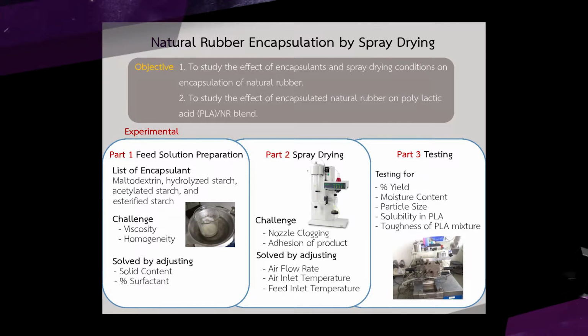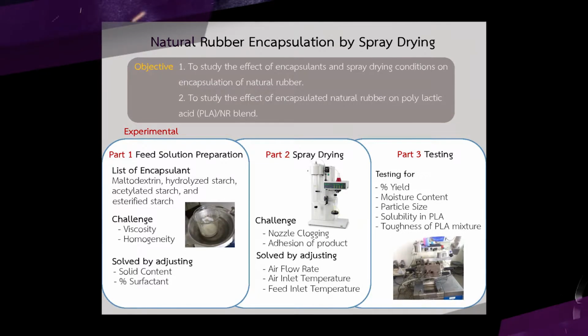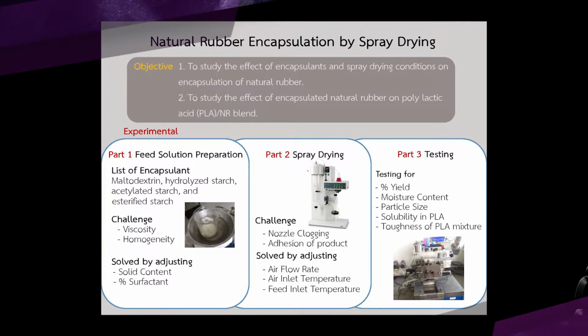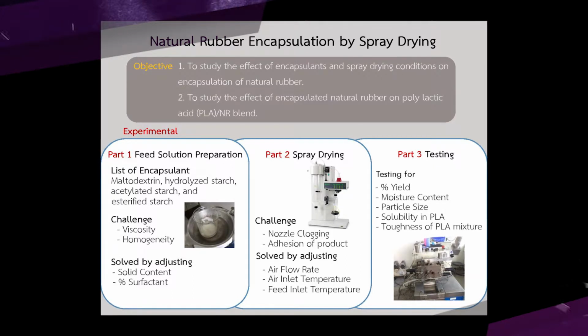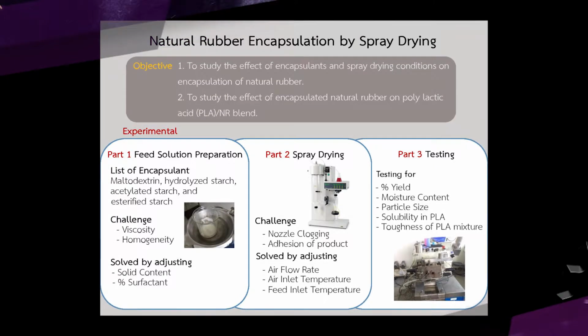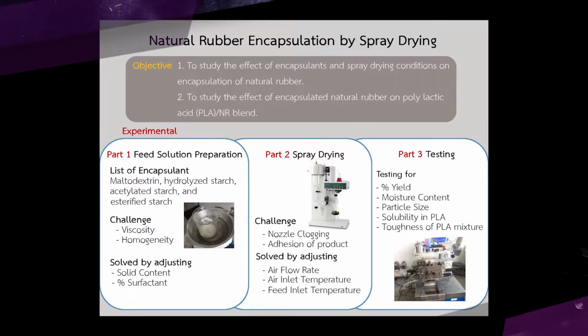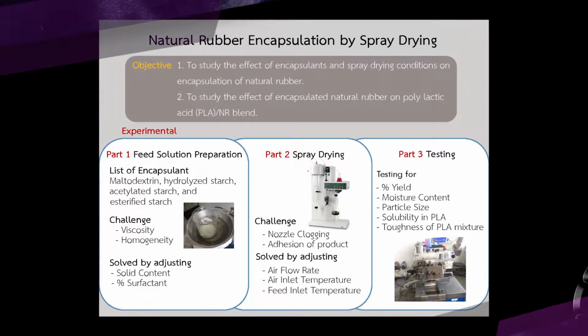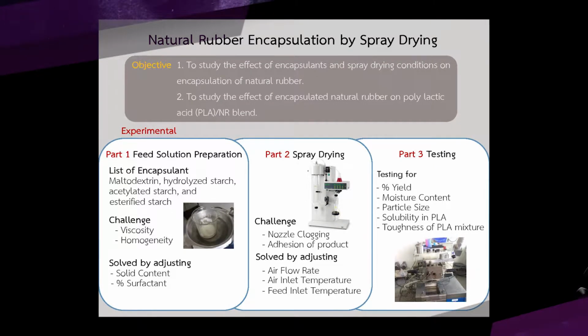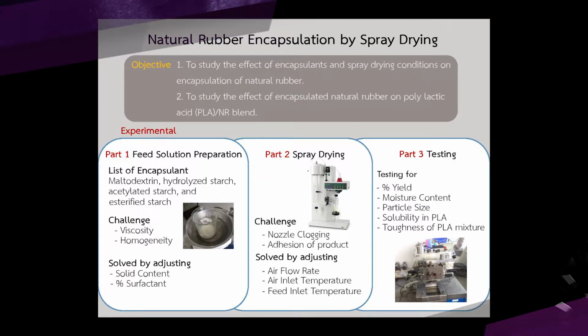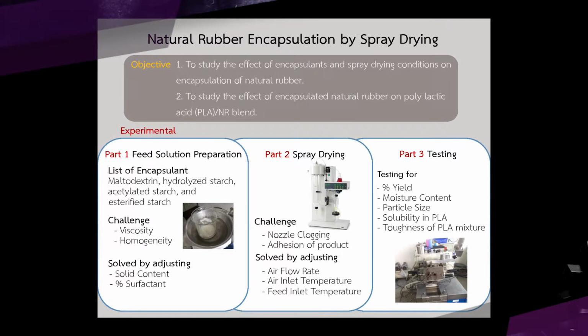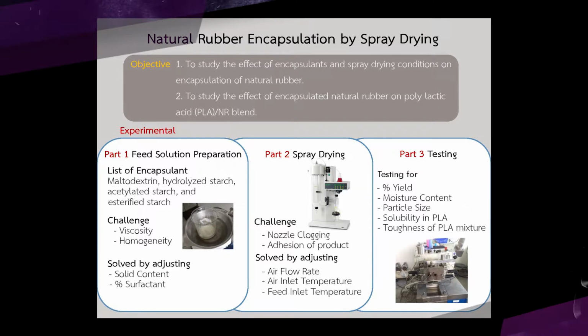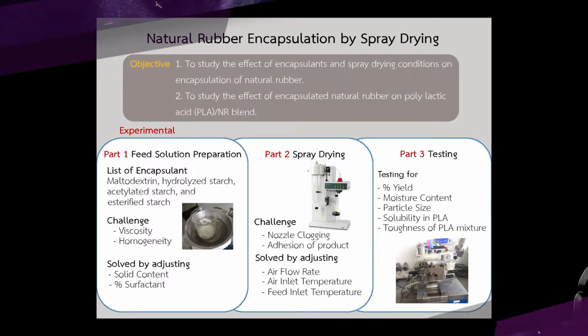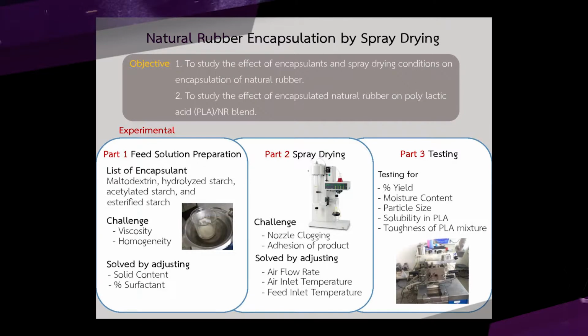If the powder gets stuck within the chamber of the spray dryer, we have to increase the air flow rate and air inlet temperature. On the other hand, if the nozzle is clogging, we have to decrease the air inlet temperature and feed inlet temperature. And our last part is testing. We will test our product based on percent yield, moisture content, particle size, solubility in PLA, and toughness of PLA mixture.